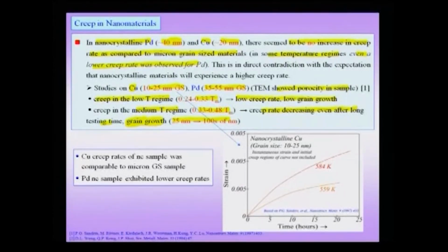Now, below is shown, for instance, the studies on this copper material, which has a grain size in the range of about 10 to 25 nanometers, and in this plot we have the instantaneous strain, which is the elastic strain, initially removed, and the initial creep regions of the curve also excluded in the plot. And if you observe this, you see that at a lower temperature, of course, the overall creep strain at a given time, suppose I take about 10 hours, you accumulate lower strain, at a higher temperature you accumulate higher strain, which is what is expected, but additionally you notice that the creep strains are continuously building up even after long hours of testing.